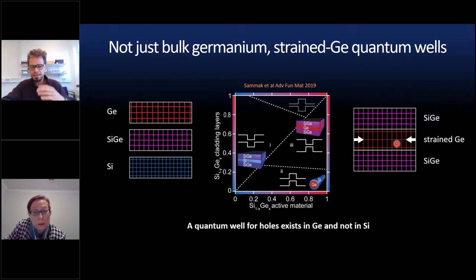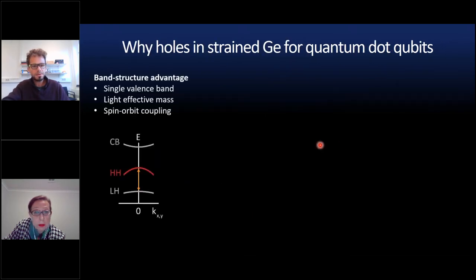And keep in mind that a quantum well for holes exists only for germanium-based structures here and not for silicon, where it's possible to confine electrons but not holes. So germanium will be compressively strained to be lattice matched, and it will host a two-dimensional hole gas. But why are we interested in strained germanium for quantum dot qubits? Well, there are a few reasons. The main one is that there is really a band structure advantage, because once you work with these strained germanium quantum wells, you get a single valence band.